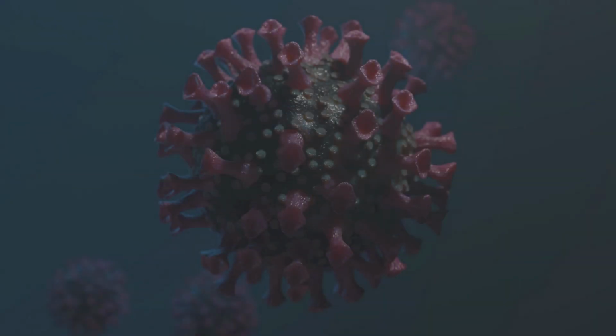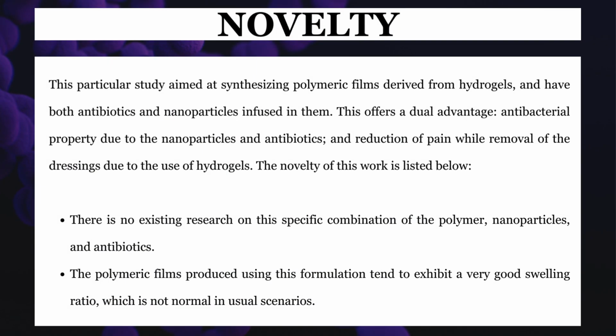Novelty. This particular study aimed at synthesizing polymeric films derived from hydrogels and have both antibiotics and nanoparticles infused in them. This offers a dual advantage: antibacterial property due to the nanoparticles and antibiotics, and reduction of pain while removal of the dressings due to the use of hydrogels. The novelty of this work is listed below. There is no existing research on this specific combination of the polymer, nanoparticles, and antibiotics. The polymeric films produced using this formulation tend to exhibit a very good swelling ratio, which is not normal in usual scenarios.